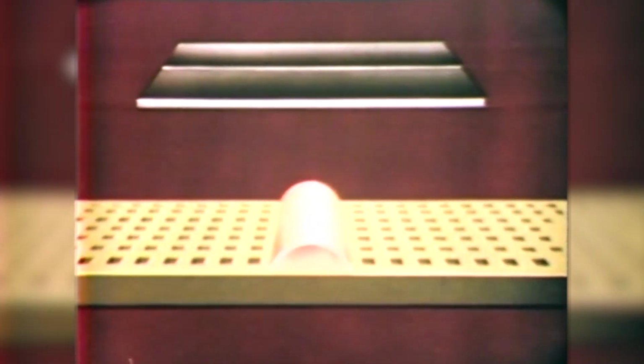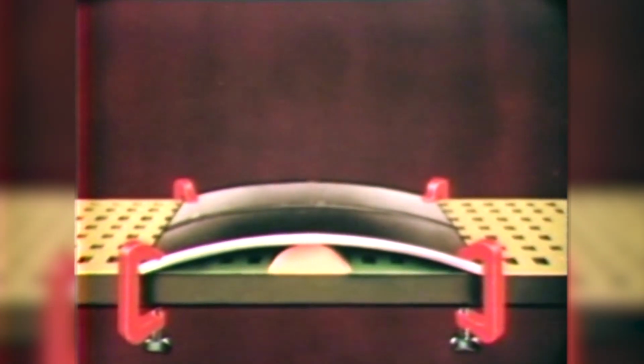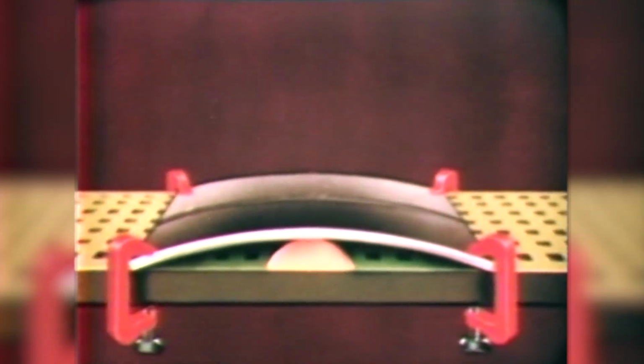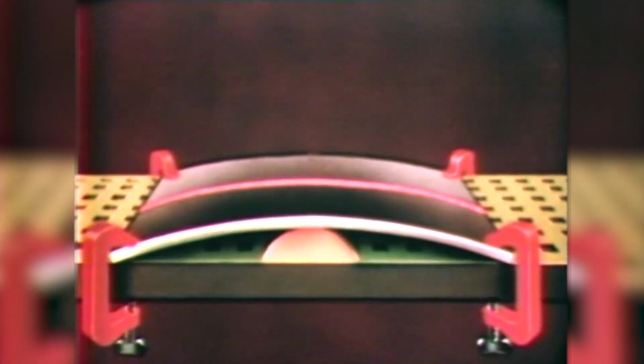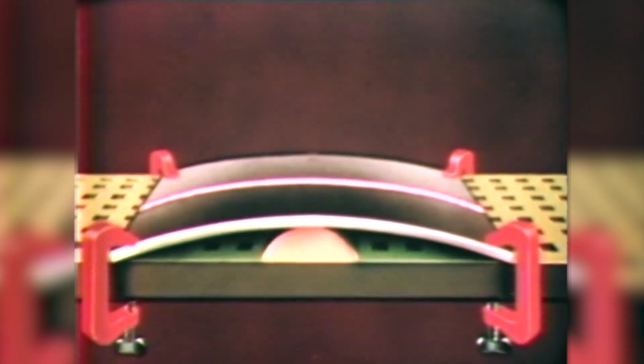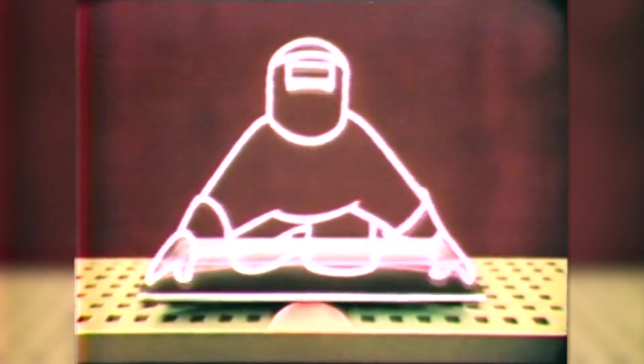We can also make shrinkage work for us by pre-bending or springing the parts involved. For example, when these two plates are sprung away from the weld side, the counter force exerted by these clamps, holding the plates firmly, overcomes the shrinkage tendency of the weld metal, causing it to yield. But we can still use Mr. Shrink after the clamps are removed. Now all he needs to do is give the plates a slight pull to remove any signs of distortion.